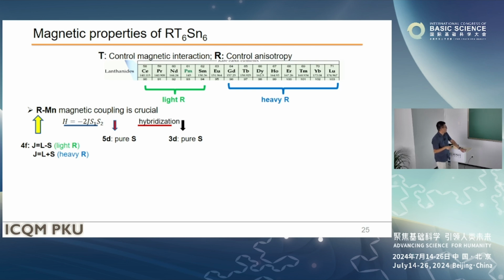So you have a Heisenberg exchange from 4f to 5d, and this number is negative, meaning your S moment is coupled with the 5d's S, and then you have some hybridization between 5d and 3d. So if you have a light rare earth, J equals L minus S, this rare earth moment is parallel with your transition metal, right? I mean that is a ferromagnetic ground state. But if you are a heavy rare earth, it's antiparallel, meaning a ferrimagnetic ground state.